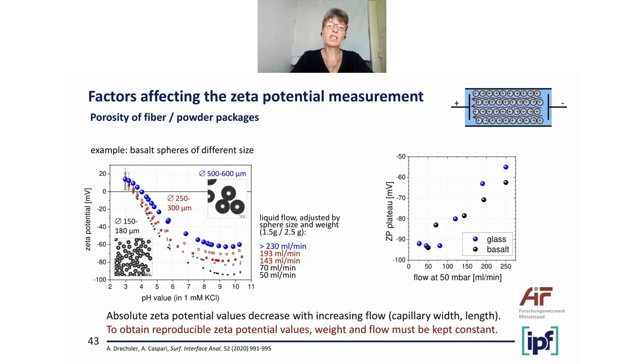And you see if the particles become bigger and the flow becomes higher, then the absolute amount of the Zeta potential becomes smaller. You can also see this in the right image, where the plateau value of the Zeta potential is drawn versus the liquid flow. The reason for this is if the capillaries between the particles become bigger, then again less of the particle surface is accessible to the measurement, and that's why the Zeta potential becomes smaller. So as a rule of thumb, for measurements on fibers or powder packages, we try to use always the same liquid flow if we want to compare different measurements.